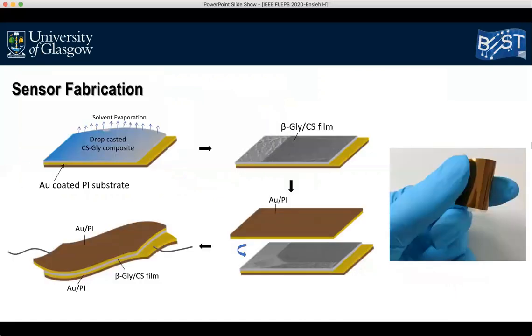So after making an optimum composite film, we made a sensor from the developed biodegradable piezoelectric composite. Here shows the fabrication process of the piezoelectric sensor. First, the gold-coated flexible substrate was prepared by depositing 100 nanometer gold on a flexible PI substrate, and then a solution